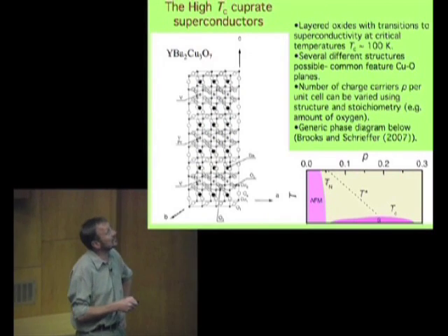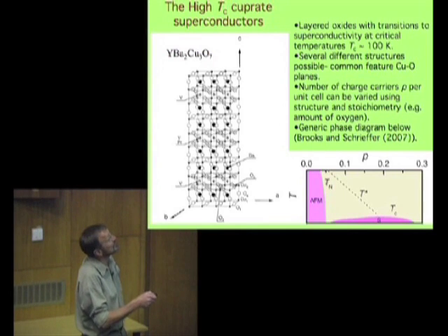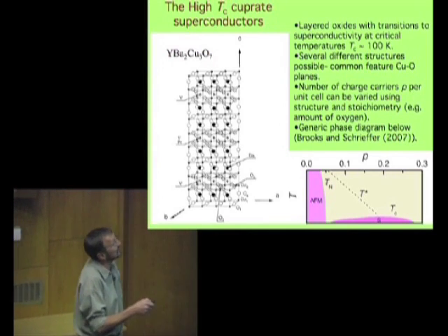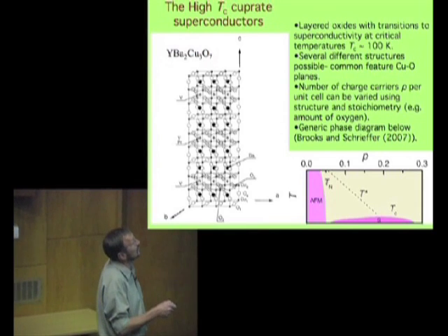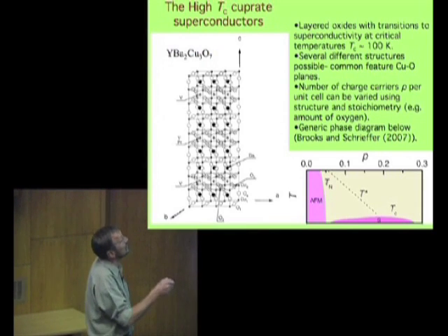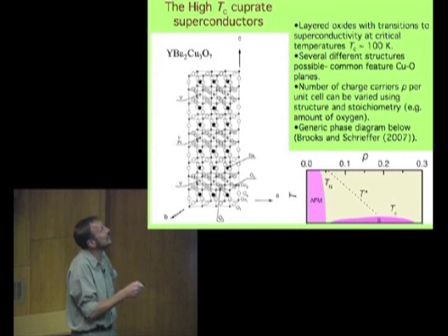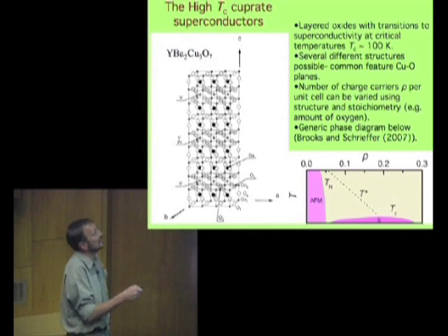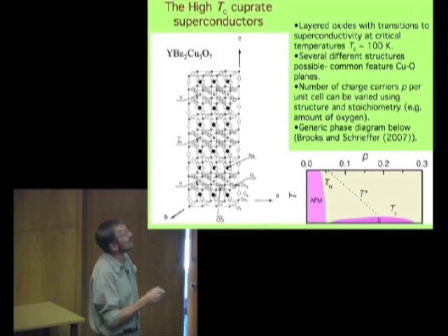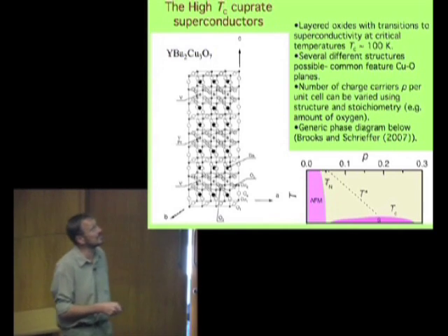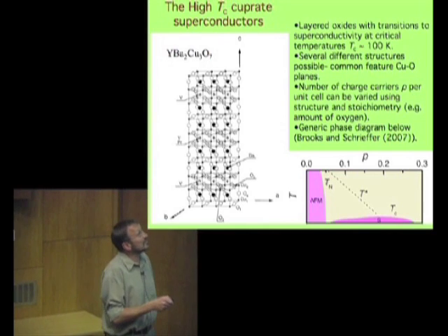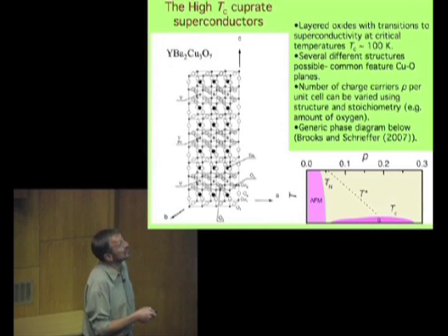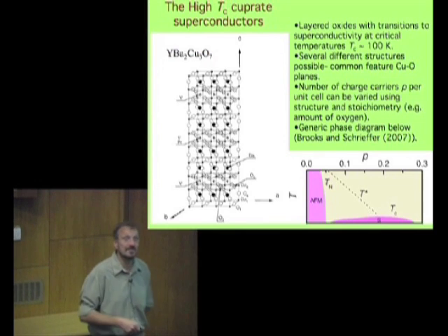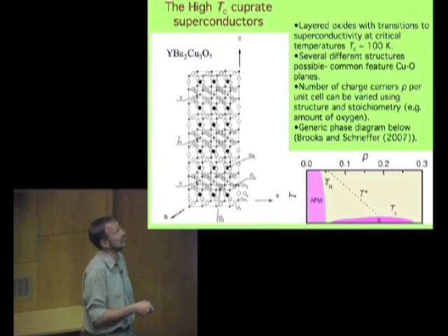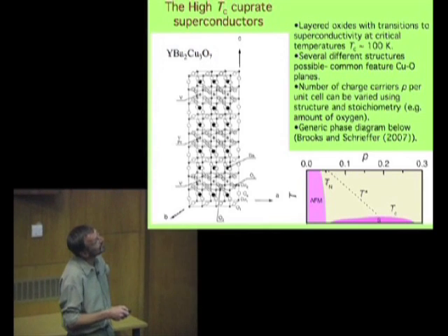So, a brief introduction to these things. This is a typical yttrium-barium-copper-oxide superconductor, the structure, and you can make substitutions of the various metals that are involved. For example, praseodymium could go in instead of yttrium. You can vary the amount of oxygen that makes it into there. But the basic, important fact about these is that these are layered materials. They're quasi-two-dimensional materials. Their critical temperatures, as discovered about 20 years ago, can approach 100 Kelvin. And so this led to vast speculation about flying trains worked by liquid nitrogen and things like that.